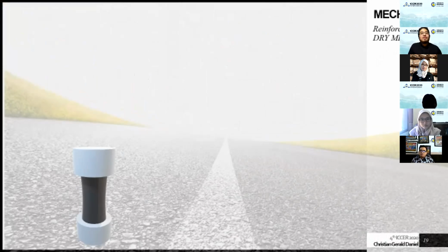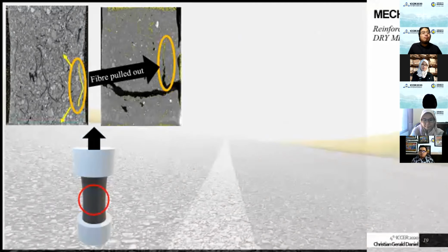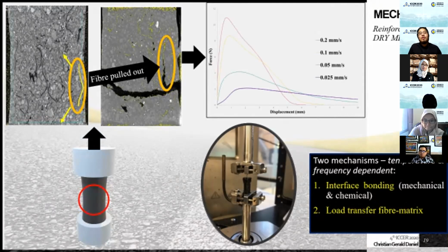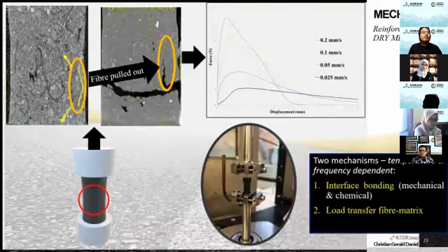And the more interesting one is how the mechanism works. Within the dry method, when we try to pull the sample and we zoom in, we can see something like this. The fiber will be pulled out, which means there is an interaction, which is both temperature and frequency of the load dependent. It has an interface bonding, both mechanical and chemical, between the fiber and the bitumen matrix. And there is a load transfer thanks to the network of the fiber, between the fiber and matrix and another fiber. So those are basically the reinforcing mechanisms.